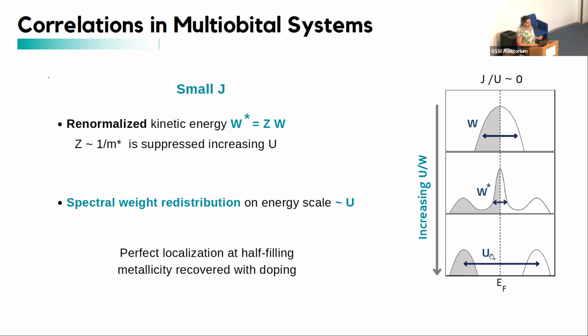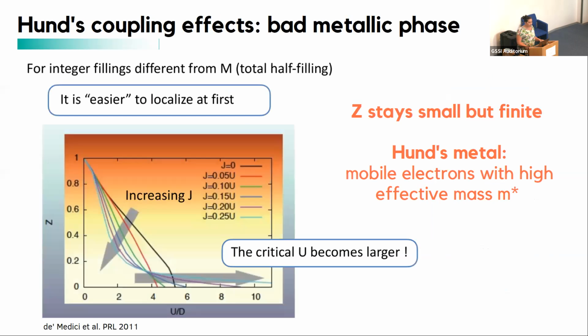And this, the energy scale that is controlling this, is the Hubbard U. You have perfect localization at half filling, the Mott insulating transition. And if you have some doping, you can recover some metallicity. That is bad if you are very close to half filling. So what happens now when J increases?